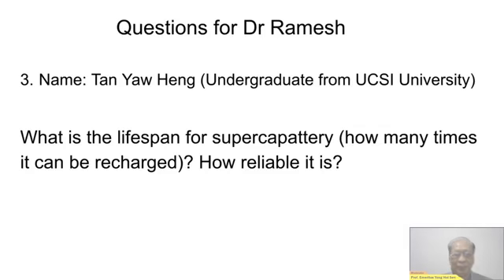Okay, regarding the lifespan of a supercapacitor, normally in academia our main core is publication and so on. For these purposes, we do charge and discharge, and they can retain high efficiency up to 90% and above. We do charge and discharge commonly for all the devices that we fabricate. We have tried more than 3,000 times. Some can even withstand more than 10,000 times. It's possible. And they also can give a high coulombic efficiency, which shows they can retain their properties over a prolonged time.